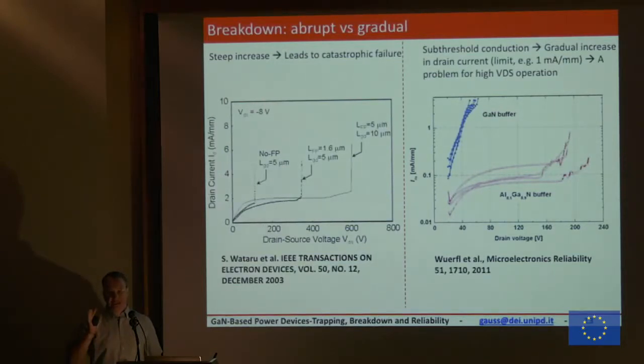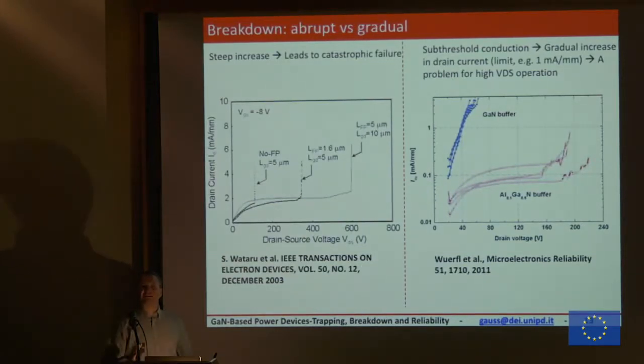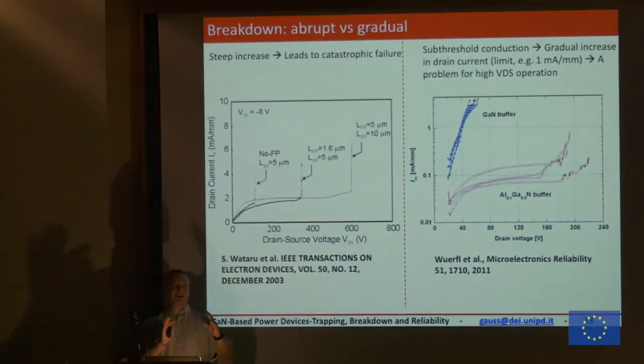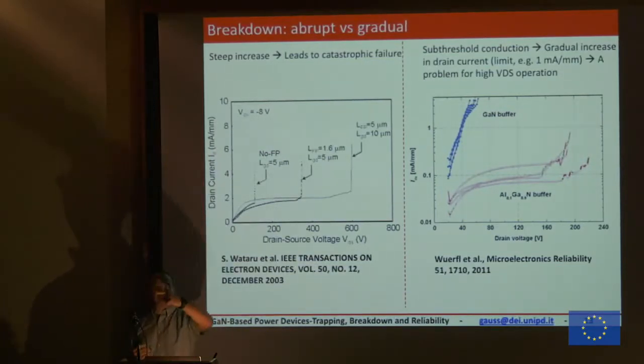This is not the case for the other power devices, specifically in silicon, where they have what they call an avalanche capability. Let's say that I have an application of 600 volts, and I want to have my devices in that application. What does the designer do? The designer says, okay, let's design a silicon device which has a breakdown around 650. We just make a little over-design. Then if during the application the voltage goes to 700 or 800 volts for a short period of time, it is not a problem, because for a short period of time your device will go into breakdown. It will be a sustainable breakdown. The device will not break at all unless the period is too long, let's say some microseconds or milliseconds, and then that is fine.